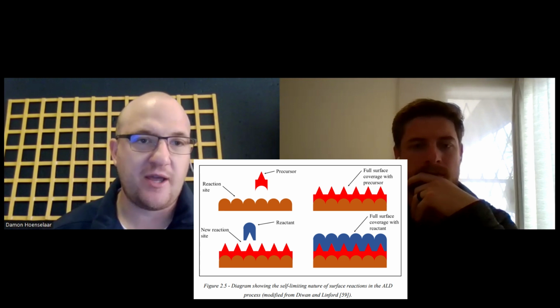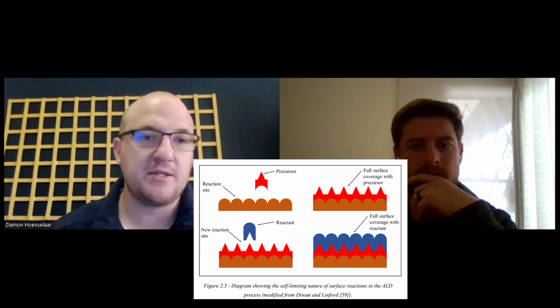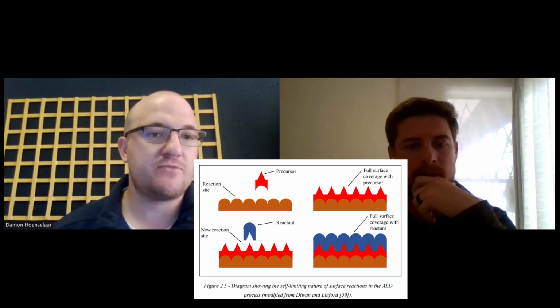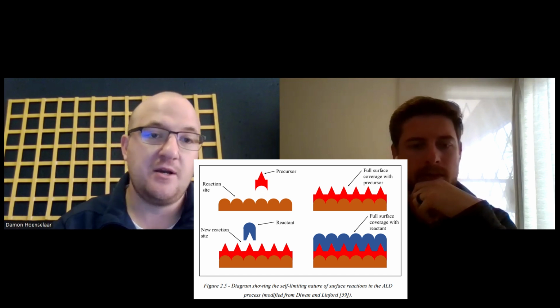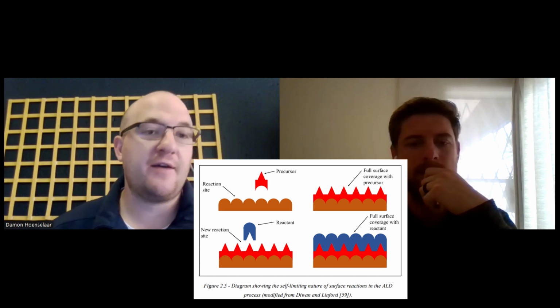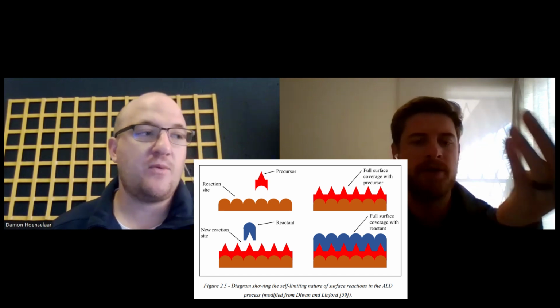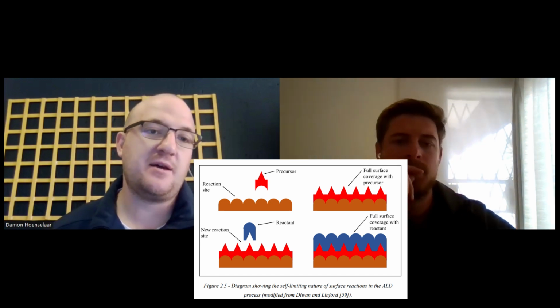You can think of a self-limiting reaction like an egg tray. Each spot on the egg tray is where you want to put an egg, and each trimethyl aluminium can fill one of these points. You can't have 2 atoms filling in a point, because it won't react with itself. As the TMA reacts with the surface, it fills in all these points until your surface is completely covered. Once the surface is completely covered, the reaction is done. It doesn't matter how much more TMA you pump into that reactor, you won't have more growth.